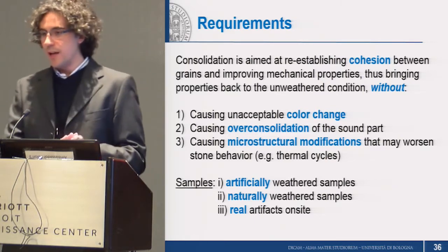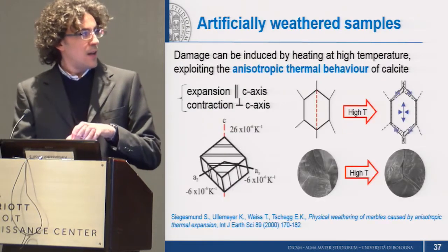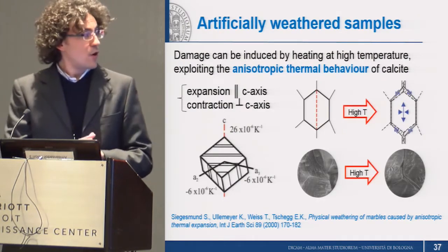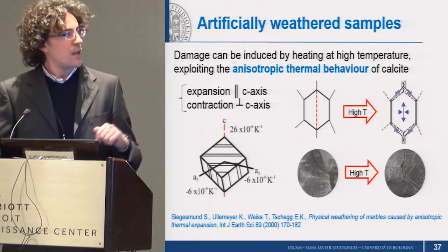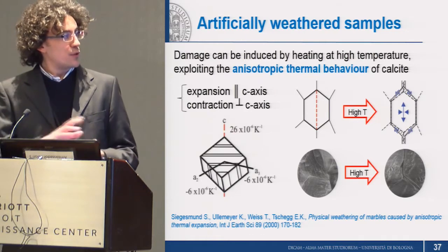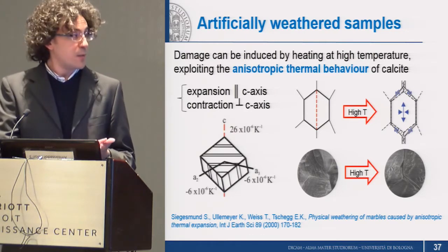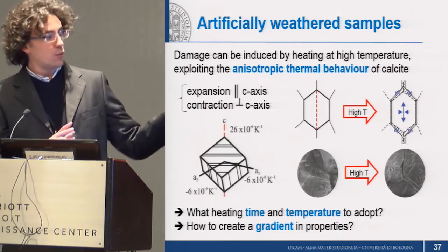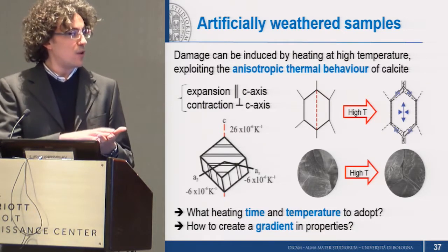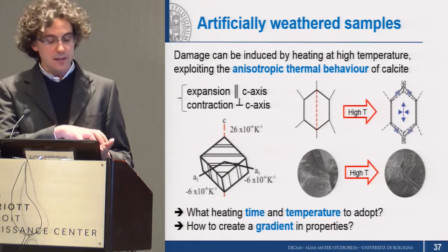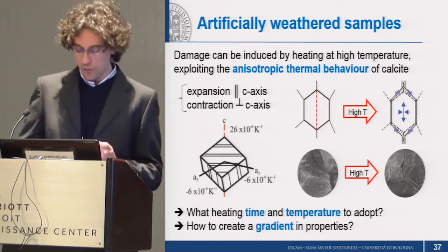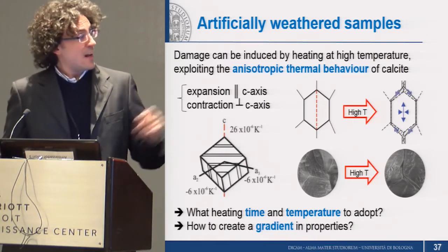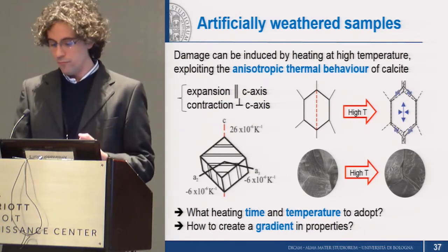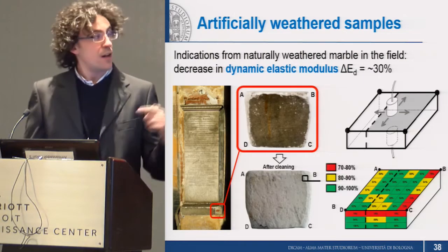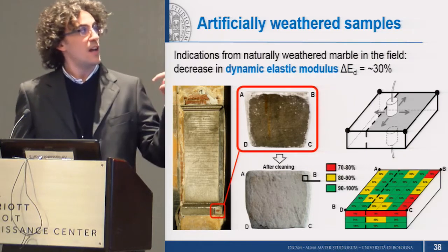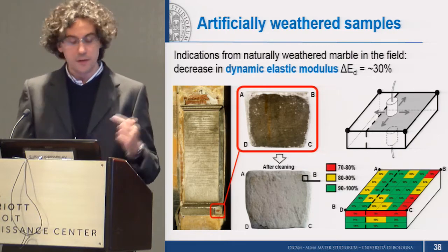So to produce artificially weathered samples, as I mentioned, we exploited the anisotropic thermal behavior of calcite crystals, which makes us able to produce damage by heating samples at high temperature for a certain time. To find out at what temperature and how long we should heat our samples, and if it's possible to create a gradient in marble properties, which is usually the case in the field, we started analyzing some real samples coming from a decayed gravestone, in this case in Bologna, and we found out that the decrease in mechanical properties, in terms of dynamic elastic modulus measured by ultrasound, is about 30%.